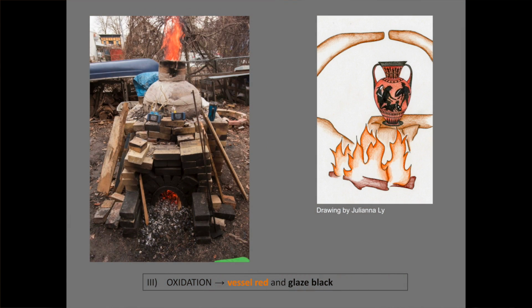Remember I mentioned earlier that the silica and potassium in the gloss are key components of glassmaking? Well, now the heat in the kiln was raised even higher to the temperature at which the painted decorations made with gloss slightly melted into a glassy substance. Because of these two components, the technical term for this phenomenon is sintering.